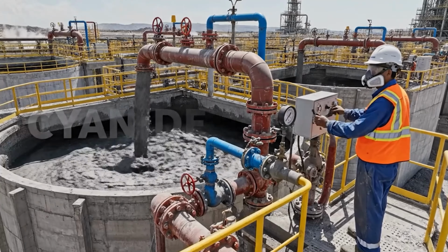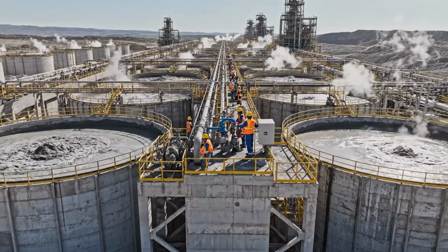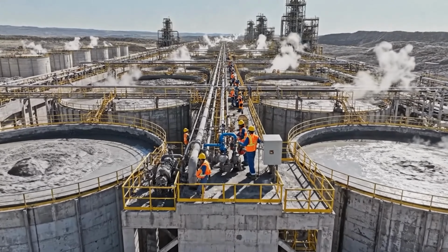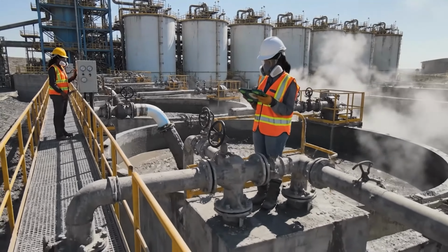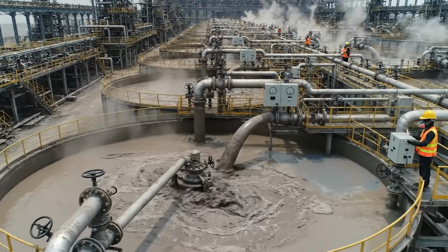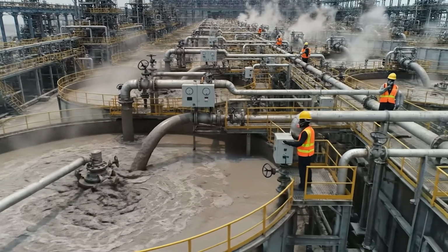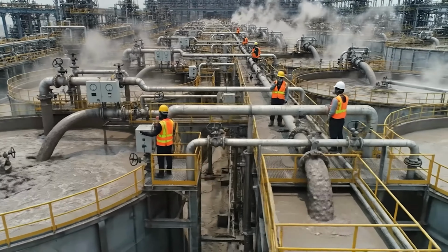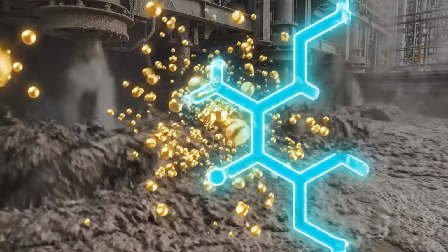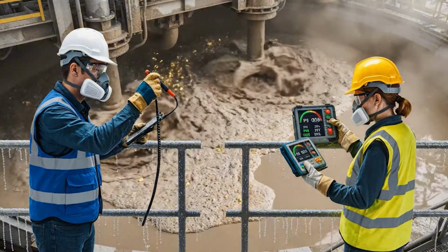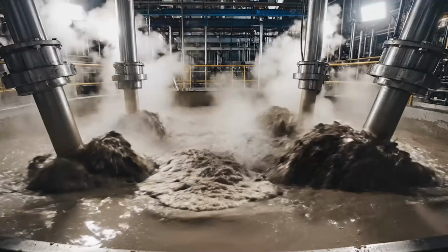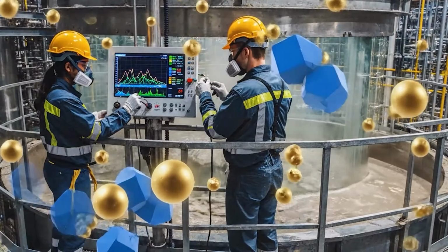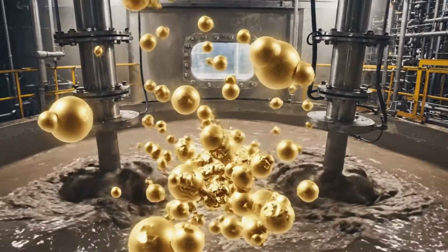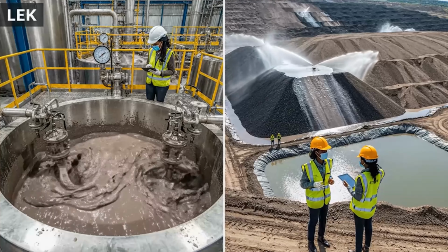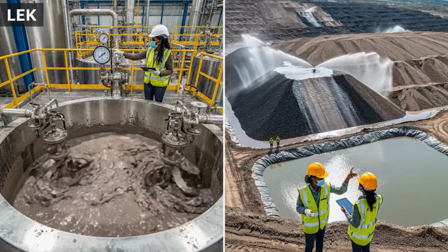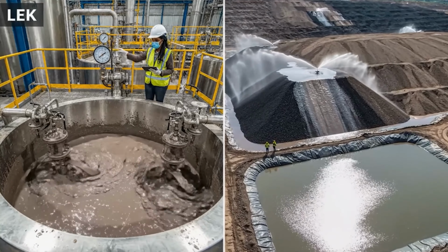The core extraction step, cyanide leaching. The finely ground slurry is mixed with a dilute sodium cyanide solution, 0.01 to 0.05% concentration, weaker than some household cleaners, in large tanks. Air or oxygen is added, and agitators keep everything moving for 24 to 72 hours. The chemical reaction: gold dissolves as a soluble complex, Au(CN)2-. This process, called cyanidation, recovers 90 to 97% of the gold in many ores.